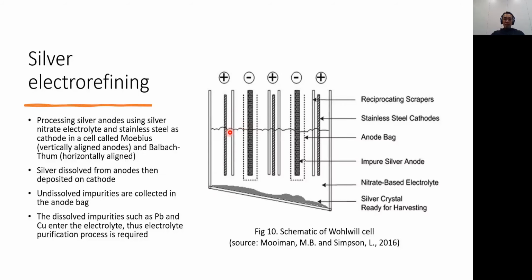So over time, silver, because it's not solid, will fall down to the bottom of the cells, and it's not cathodically protected. So silver here can be redissolved into the electrolyte again because of the free acid content. That's why the free acid in silver electrolyte is quite limited, at a low point, maximum 10 grams per liter. While in gold, it can be 100 grams per liter, the free acid.